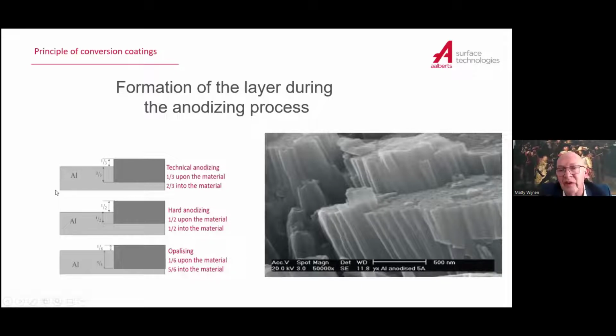The same counts when you look at anodizing. It's not, as I said, an electrolytic process, but with electrolytic help, we form an aluminum oxide layer. We use the aluminum of the part itself, and we put it in the tank. When it's in the tank, it's dissolved. The tank contains mostly sulfuric acid. The aluminum is dissolving on the surface, and due to the forming of oxide, aluminum oxide is formed and builds up onto the material. And what you see is that all the aluminum oxide layers, the anodizing layers, are formed out of the material itself. And that's why it's a conversion coating.